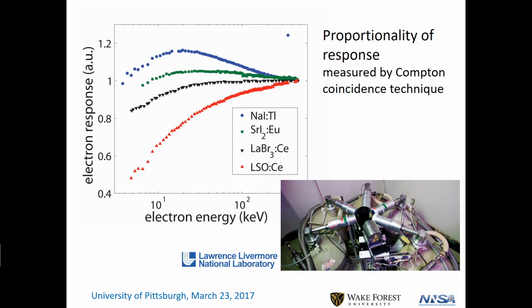they can produce Compton electrons, can produce photoelectrons with Augers that follow. So it's loads of pathways to stop a gamma. And even when you've stopped it and you launch a high-energy electron, there are loads of ways for that electron path to split going down, and it splits at different energies. So you're always doing a big averaging over this energy scale. So whatever departure from a straight line you have will turn itself into an increased line width, and that's the loss of resolution. And so this was the big problem. The sponsors say, get rid of that curvature.